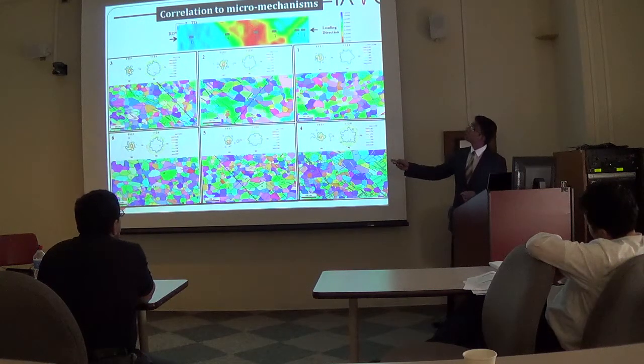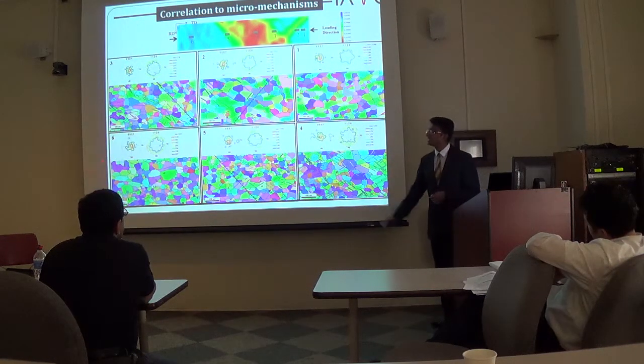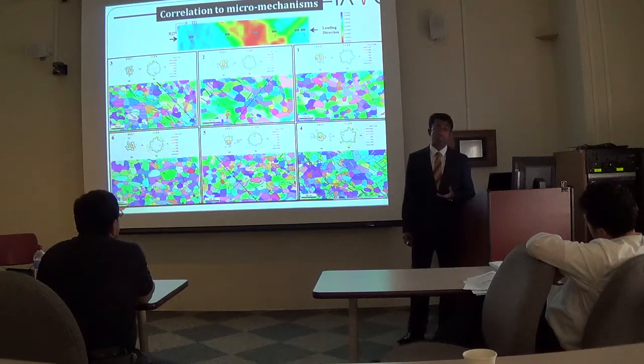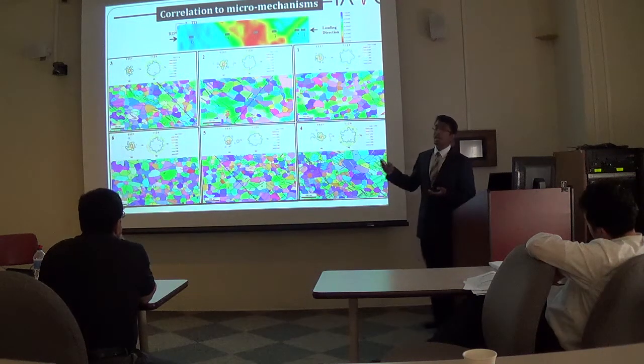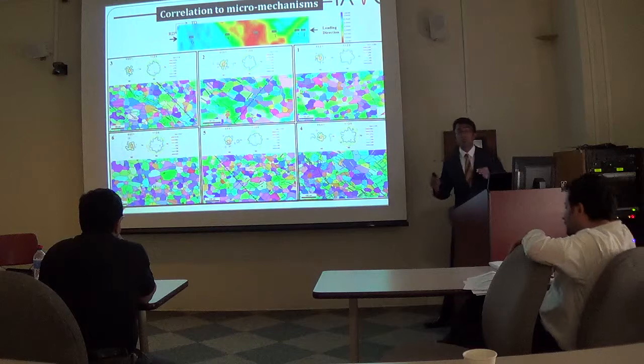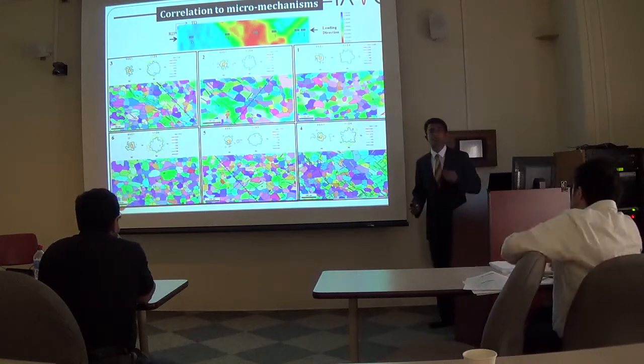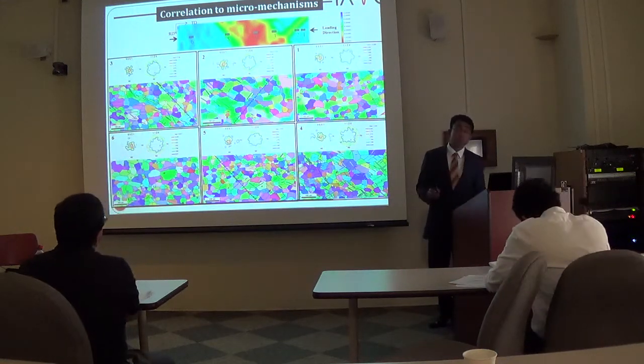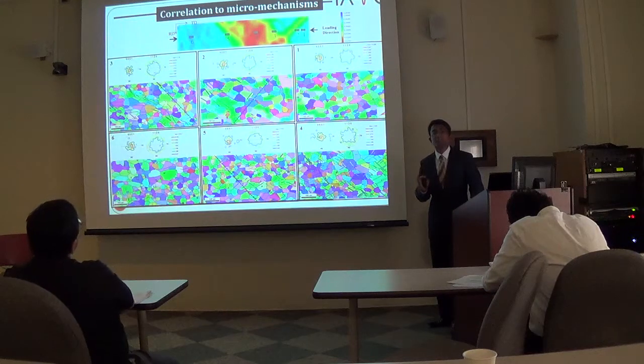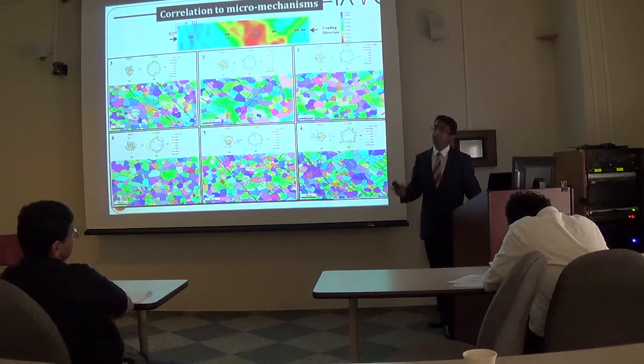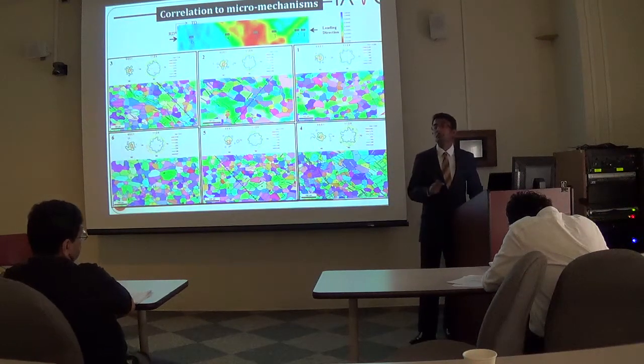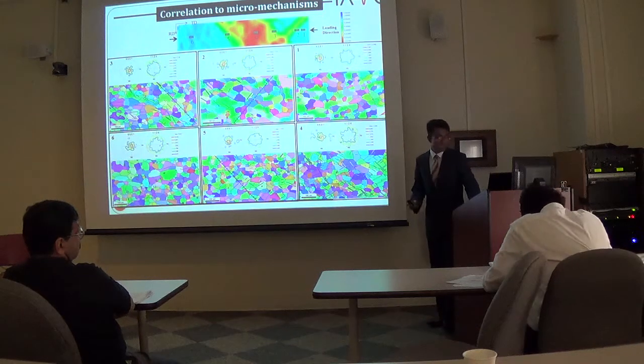While the regions outside the strain band, for example 6, seem to be much clearer of twins. Thus, you can see how these strain bands were actually indicative of localized micromechanisms that activated the material. But what is important to see was how the AE wave signatures, which were collected in real time, were also able to track this evolution of the active micromechanisms in the material.